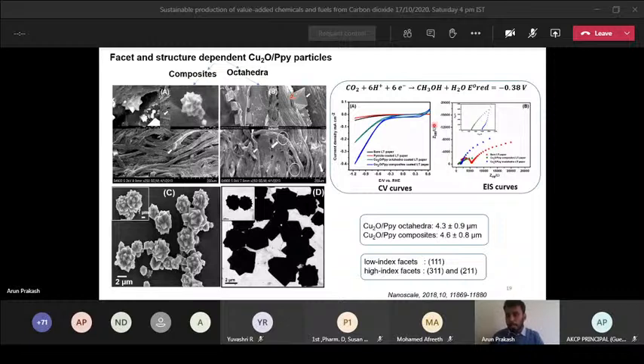You can control the potential applied to your working electrode by using a potentiostat, and you can use a technique like cyclic voltammetry. In cyclic voltammetry, you sweep the potential to more negative potential, and you sweep back again to the initial potential. When you do this in a CO2-saturated electrolyte, you can observe an increase in current with increase in CO2 reduction. The blue curve is for the composite paper with the flower-like morphology, whereas the cyan-colored curve is for the octahedra-shaped particles. So almost twofold higher CO2 reduction activity we can achieve.